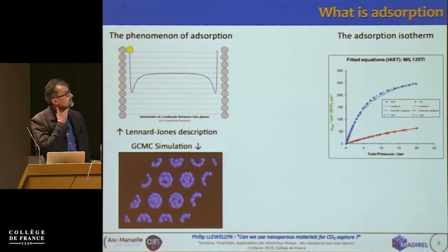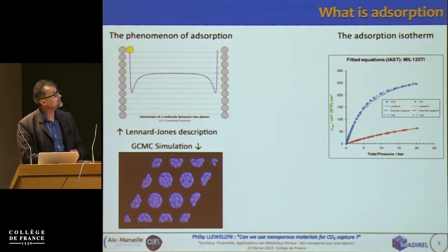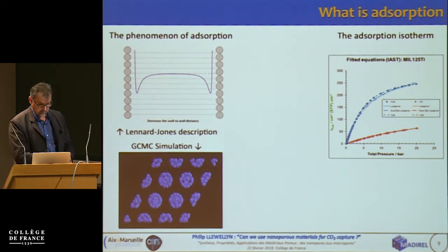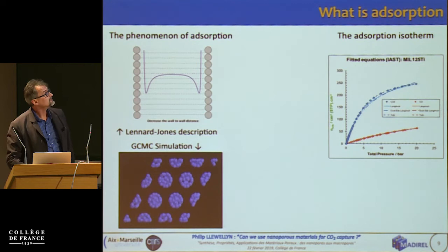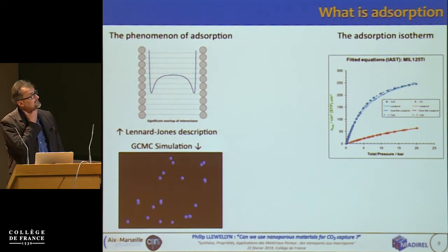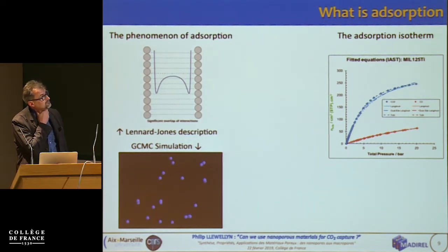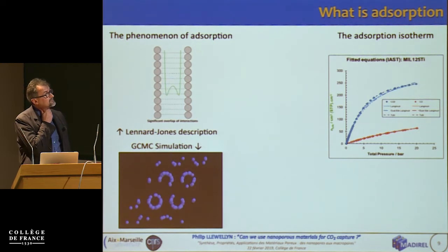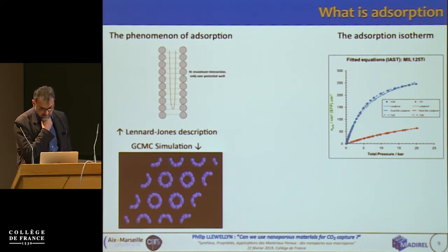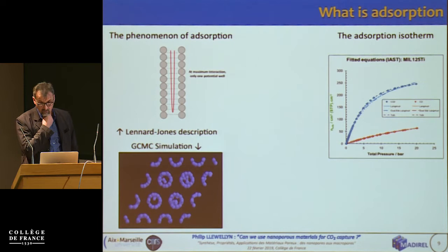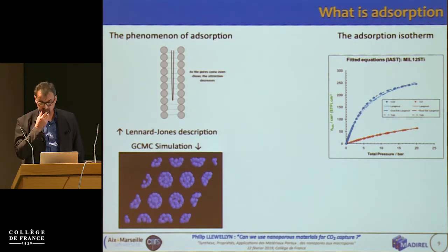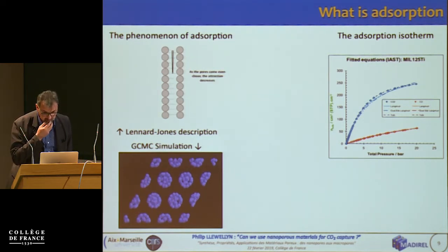Experimentally, what we can measure is an adsorption isotherm, and this is what we have here. So we have the uptake as a function of pressure, and what we have here in blue is CO2, and what we have in red here is methane on a MOF, again, probably one of Christian's materials.